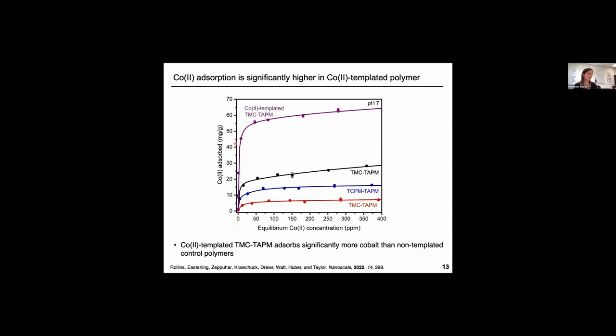We also tested this same material for its ability to capture similar divalent transition metals like manganese, nickel, or zinc out of water. And this cobalt templated polymer ended up being very good at capturing all of those metals. And you can look at that in one of two ways. You can recognize that this templating step has really improved the transition metal binding capacity of a material, or you can feel disappointed that we haven't installed selectivity for cobalt in terms of trying to capture cobalt from a mixture of very similar ions. I recognize that's a very high bar to set for my research group.